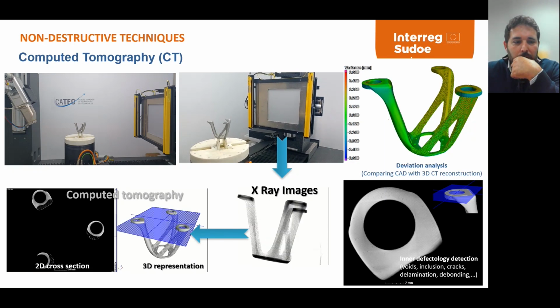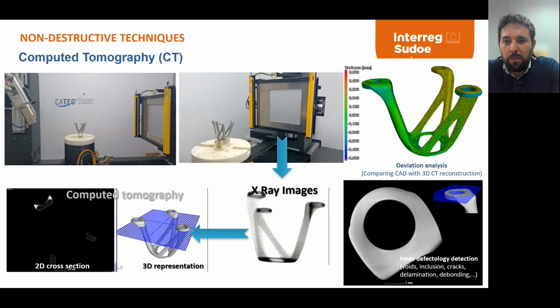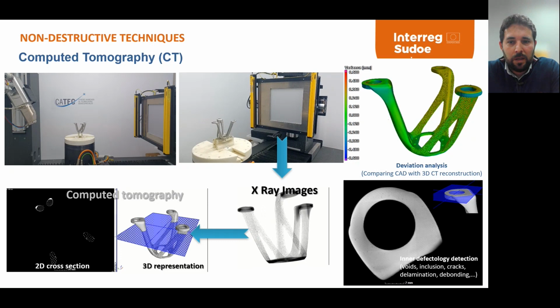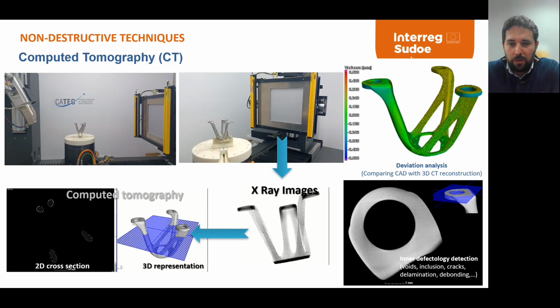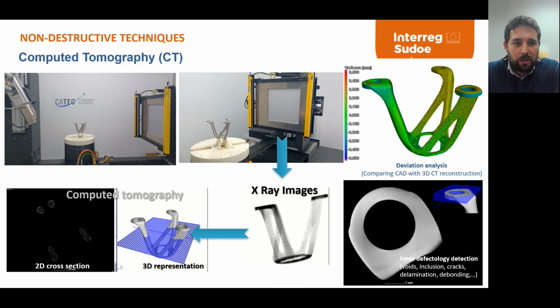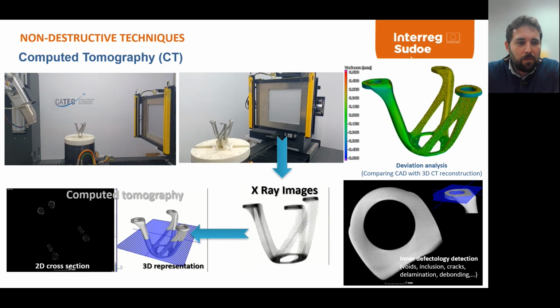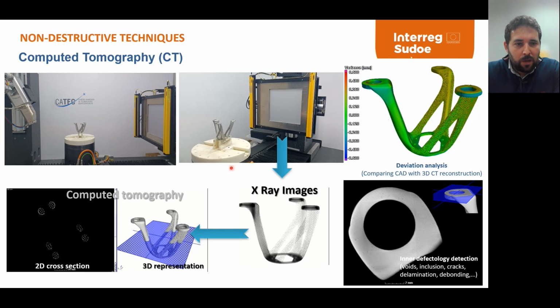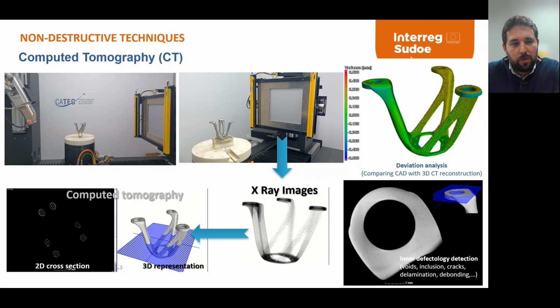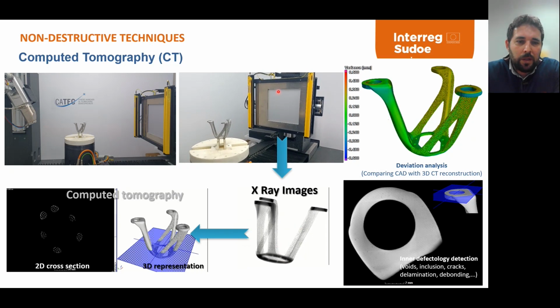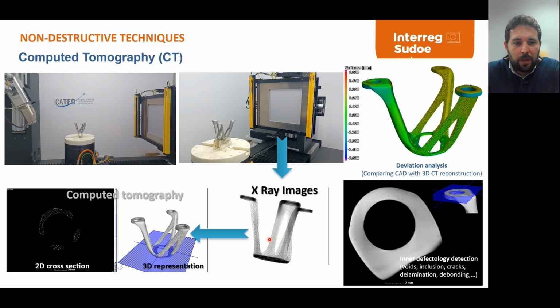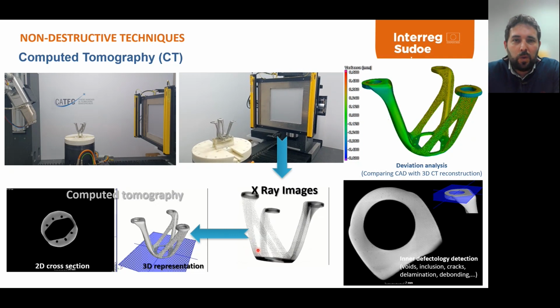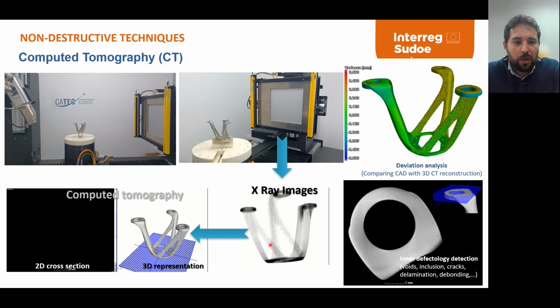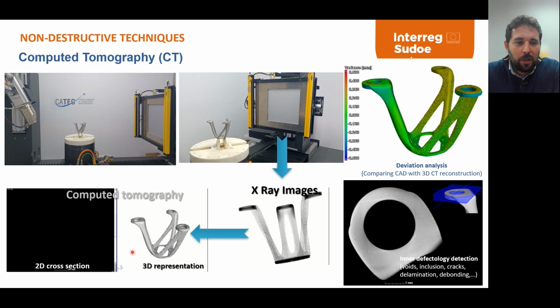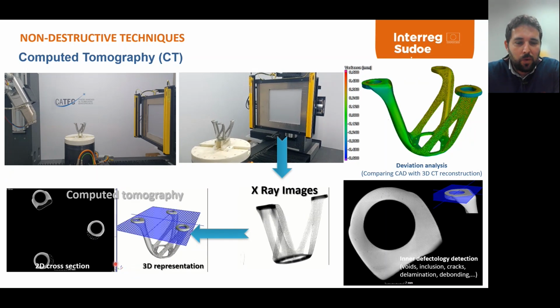So, computed tomography. Computed tomography uses the same physical principles as radiography testing, but this time you need several radiographic images to generate the CT dataset. As you can see in the image, the part is placed on a rotation platform. You shoot with X-ray. This is the X-ray tube, and the X-ray images are generated in the digital detector. When you obtain between 800 and 2,000 projections, you compute those images and you obtain the CT, the computed tomography dataset.